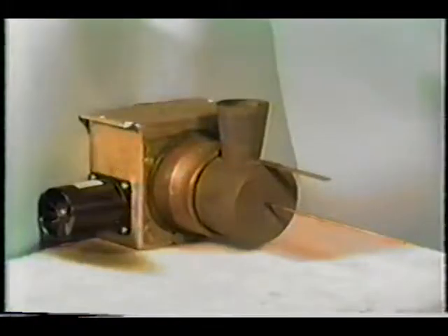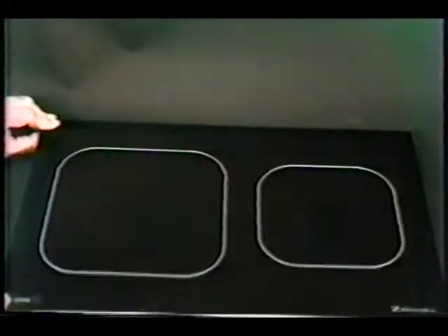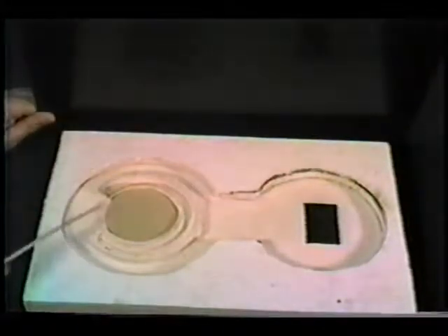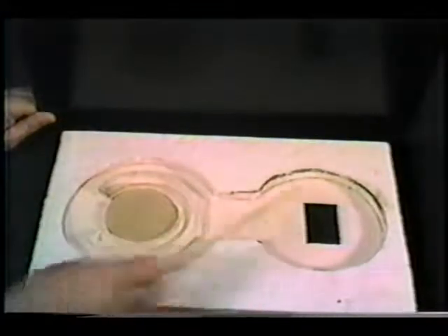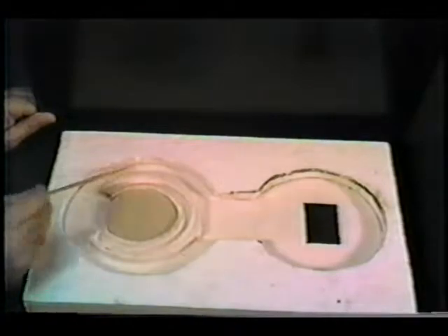In the latest development effort, a burner with a maximum firing rate of 9,000 BTUs per hour was developed for a 2-station cooktop. This burner allows the main cooking surface to be regulated to any desired temperature between ambient and 1,000 degrees Fahrenheit. The secondary cooking surface is heated by the exhaust gases leaving the main cooking station. This makes its temperature cooler and dependent upon that of the primary heating surface.